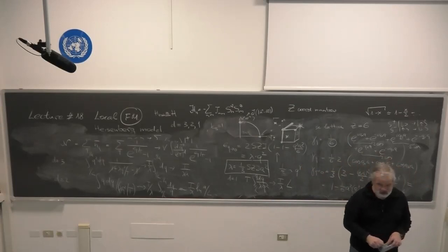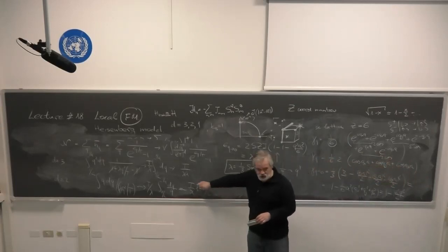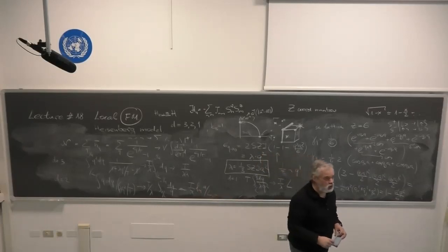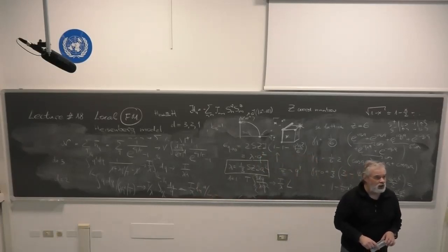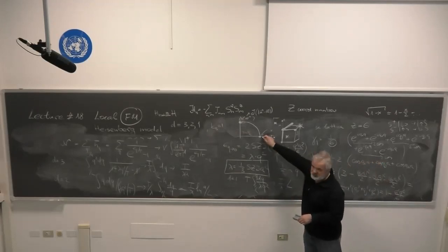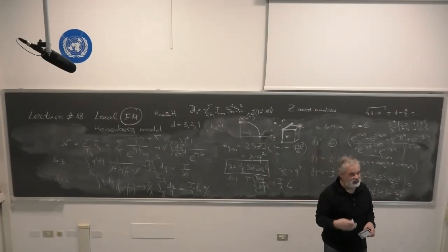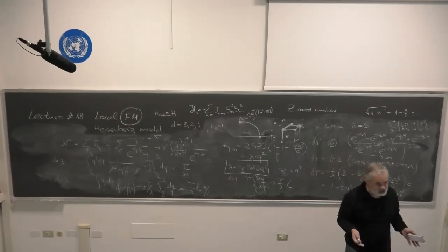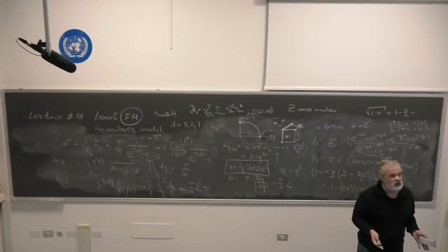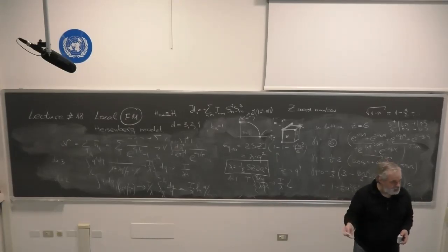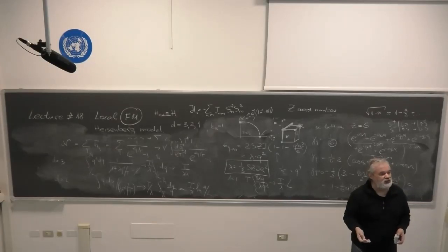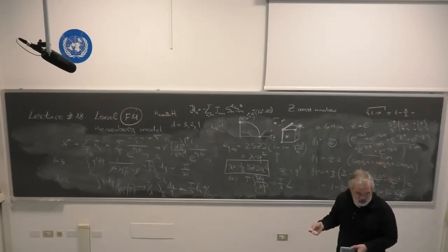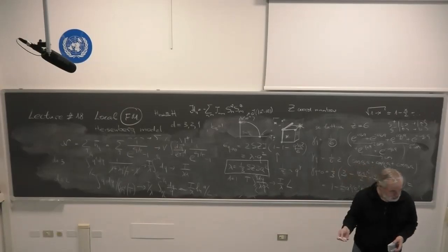Moreover, for a two-dimensional system, you see that the phase transition occurs at zero temperature, and this is the so-called quantum phase transition. What we see in all examples before, that the phase transition, this is a three-dimensional case, is driven by temperature fluctuations. And if you are at zero temperature, the phase transition is driven by the Heisenberg uncertainty principle. So this is a completely different type of phase transition in a sense. And since it is related to the Heisenberg uncertainty principle, it is called quantum.